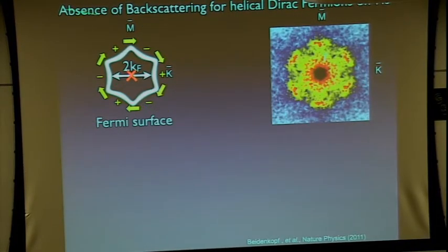Okay, so here is our simplified Fermi surface of bismuth antimony or bismuth selenide. They all look basically the same. As you go closer to the Dirac point, it becomes more circular. As you get far away from the Dirac point, it develops this sort of anisotropy. And I think it was Liang Fu that first proposed that this anisotropy itself can also be reflected in the spin texture of the surface electron.